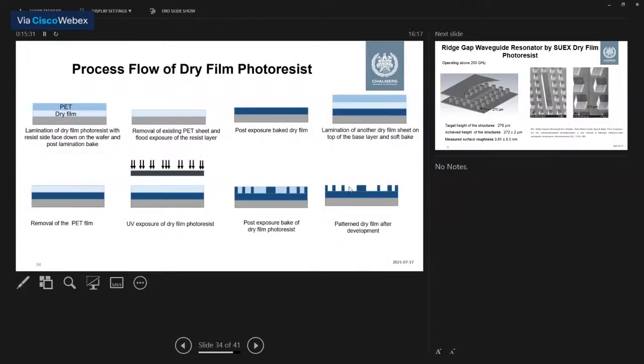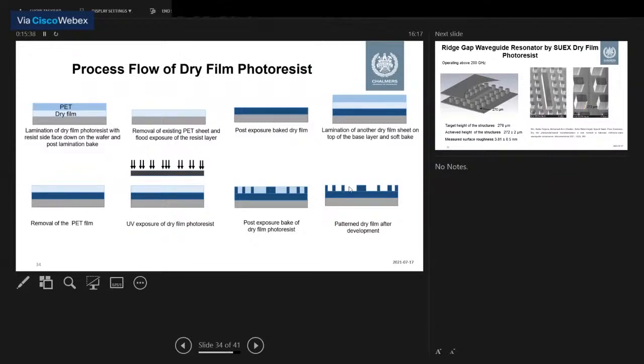So the processing step is we remove the plastic sheet of one side and laminate it on a substrate. We remove the plastic sheet or the PET sheet of the other side, and then we expose it with the required mask. So if you want a dry film substrate, then you need to flood expose it, otherwise you can just start working with it. And then after the lamination and the flood exposure, you remove the plastic sheet and start laminating another dry film sheet depending on the thickness that is needed. And then finally you will get the final pattern of your dry film photoresist.